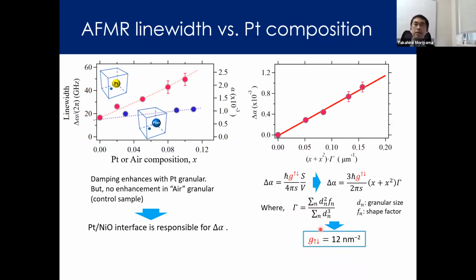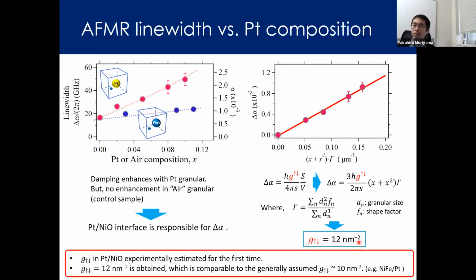We estimate the spin mixing conductance G up down, which characterizes the spin pumping effect, using the granular size and the shapes taken by the microscopy images shown two slides ago. We quantitatively estimate for the first time the mixing conductance to be 12 per nanometer squared, which actually turns out to be comparable to the ferromagnetic case. For instance, this value is very similar to the permalloy platinum interface.